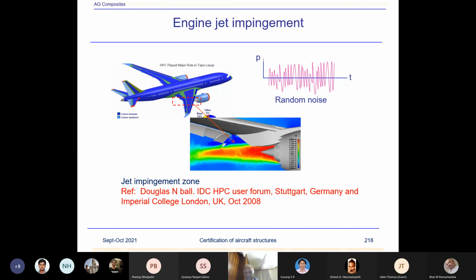So it's a complex analysis. It's not simple, in fact. So we had to demonstrate by test. However, Boeing has historically got a lot of data for demonstrating compliance using sonic fatigue on metallic aircraft. Those methods have been developed over a long period of time, and composites also. In fact, for composites, we were the ones who had to determine the compliance for the sonic fatigue of all these components using analysis and test.